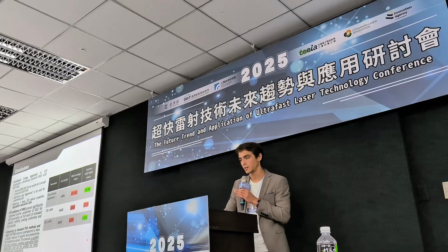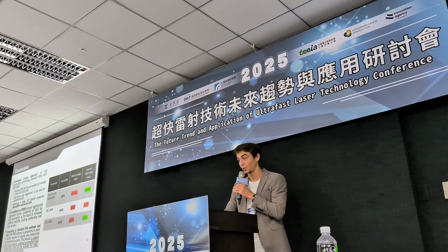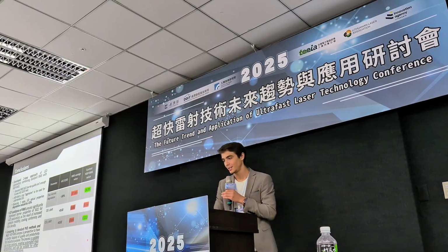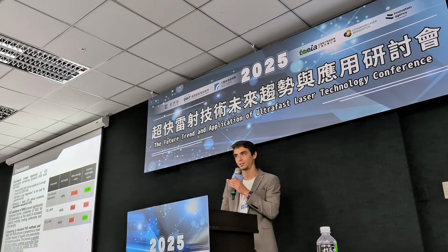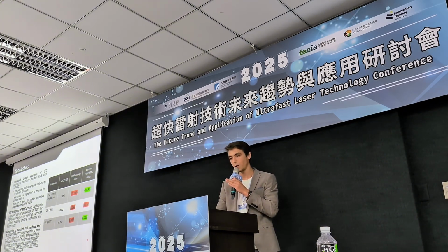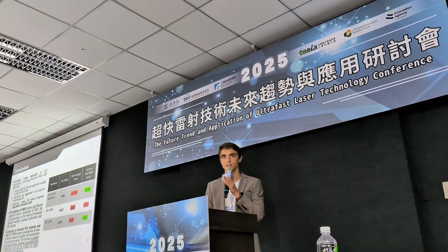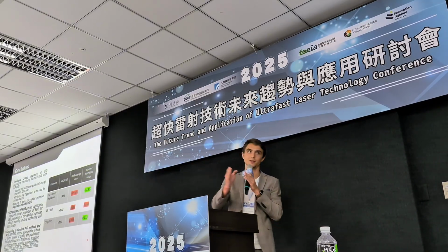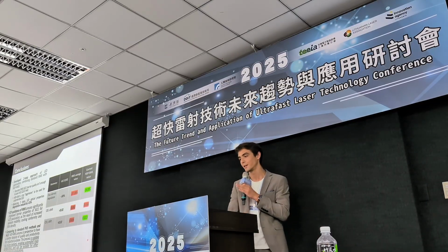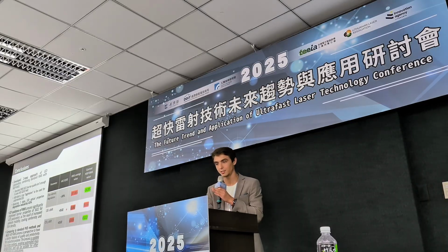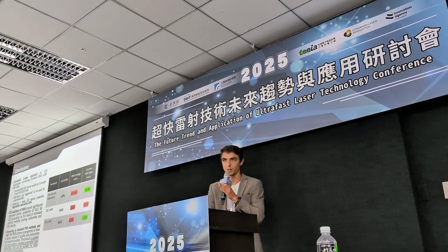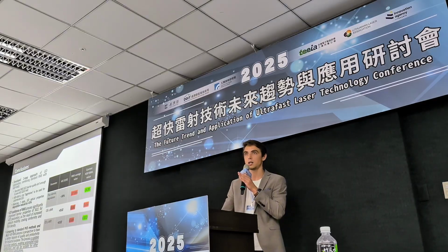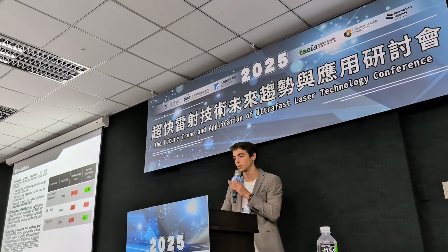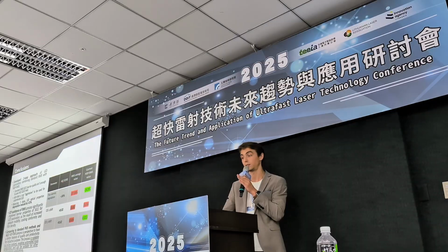Okay, and here is the conclusion. We tested a two-step approach to LED passivation, including reactive magnetron sputtering in standard regimes and high-density plasma regimes. Our results showed that they cannot work separately: either it will not pass the environmental stress test, or the LED will fail immediately after the coating. But combining standard reactive magnetron sputtering with high-density plasma reactive magnetron sputtering, we achieved some improvement, at least 25% improvement in retention of optical properties of the LED, and most of the AEC-Q102 parameters passed the test.